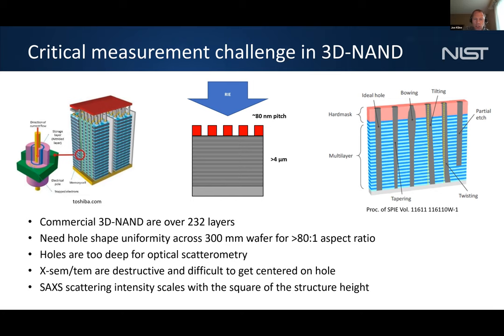And then they deposit all the different layers to create the flash cells at the same time so that it's a parallel process. And the current structures can be up to like 10 microns tall, and you have essentially a 40 nanometer wide hole that is 5 to 10 microns tall, and it has to be straight. On the right side of the screen, you can see some of the various things that can happen when you're doing the etching, where you could have various excursions from what you would optimally want. If it's not straight, that changes the way the flash cells work. And if you start having twist or tilt, you can end up having a bit shift in there. None of those are very good.